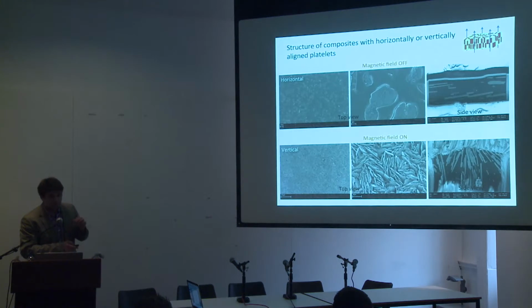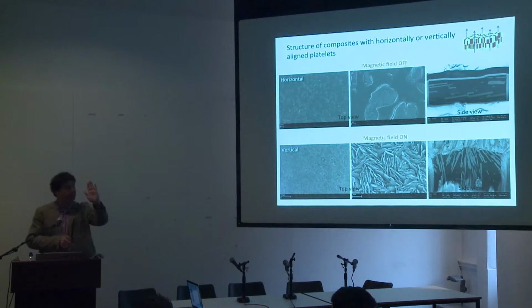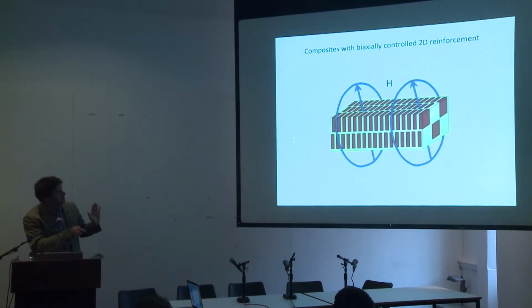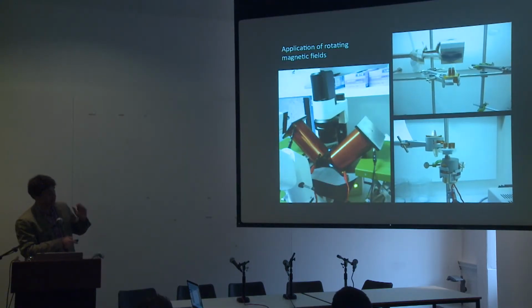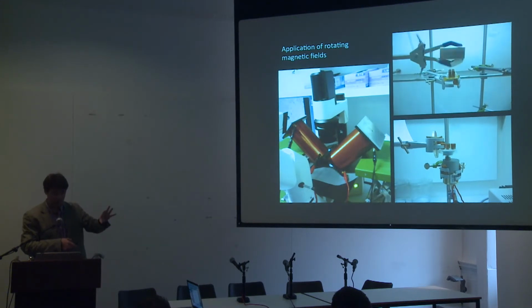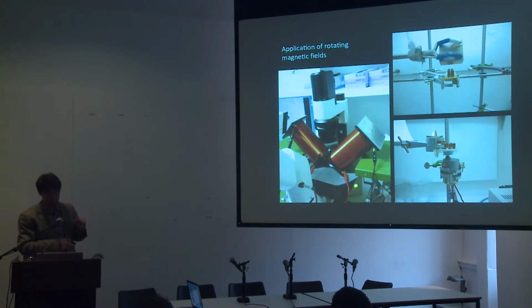So one problem if you work with platelets is that you see them all sticking out, but if you use a static magnetic field like this, you don't get control over the second axis of orientation, and that limits the maximum concentration of platelets you can get. So to solve this problem, you can actually rotate the magnetic field to force them to align into the plane of the rotating field. And here are some of the ways. These are all proof of concept experiments at very small scales, but in principle, there's nothing that hinders this from being applied in bigger structures.